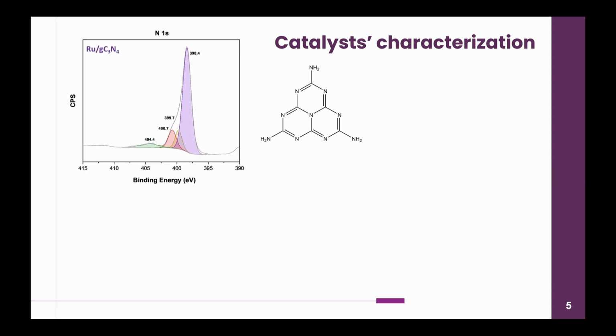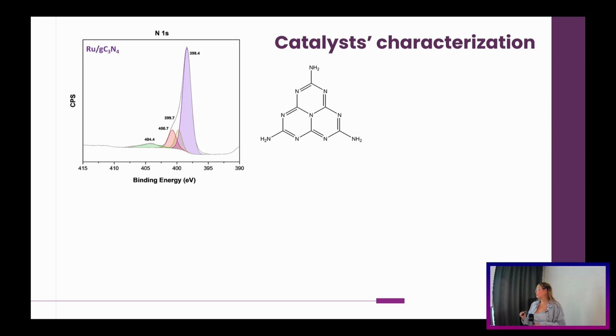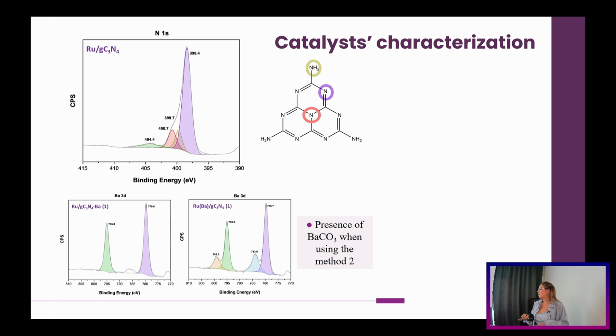In the nitrogen XPS, we observe the characteristic peaks of the C3N4 with the sp2 nitrogen of the triazine units, the nitrogen of the amino groups, the quaternary nitrogen, and the last peak is from charging effects. In barium XPS of the barium catalyst prepared with 1 millimole of barium, we see the presence of barium carbonate in the catalyst prepared by co-impregnation, as indicated by X-ray diffraction.